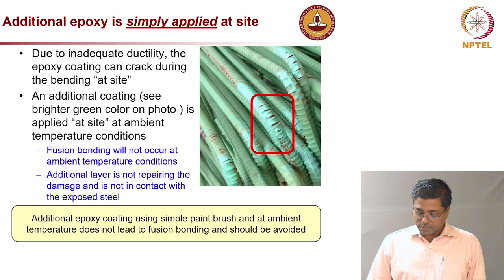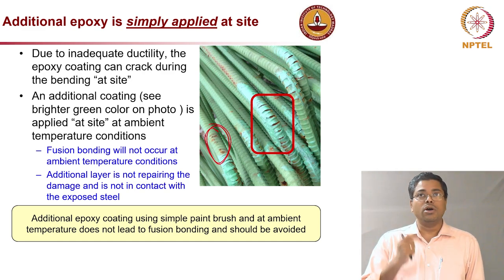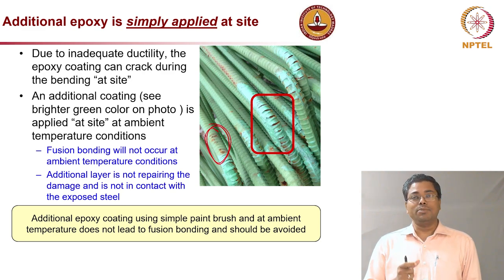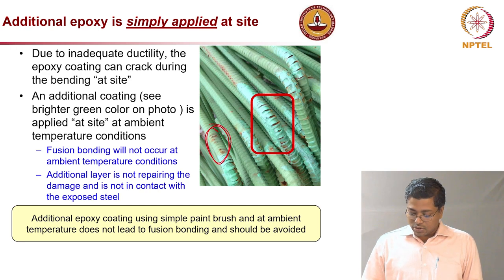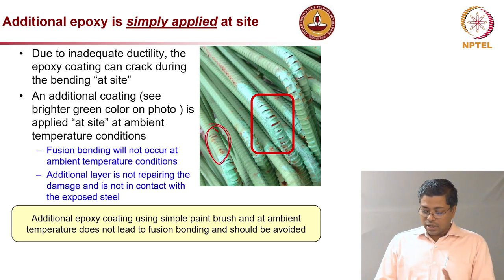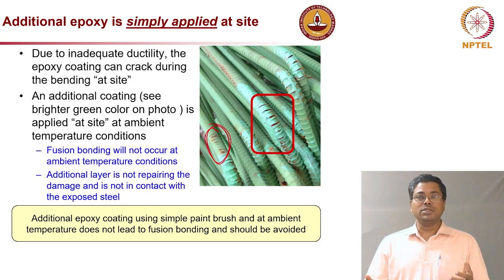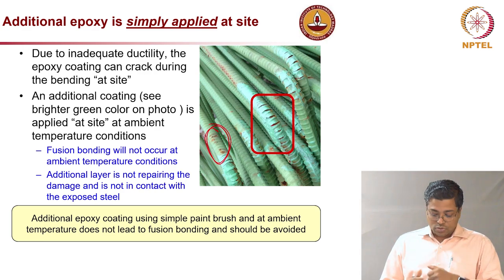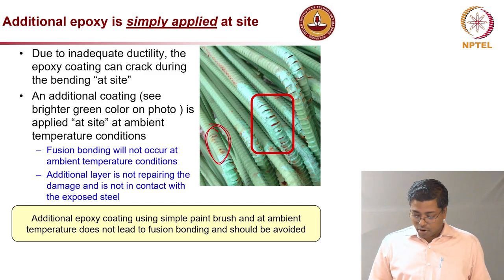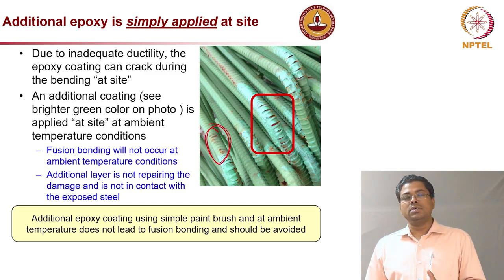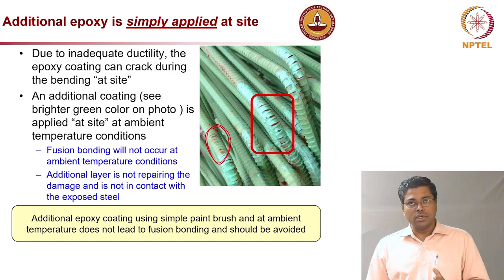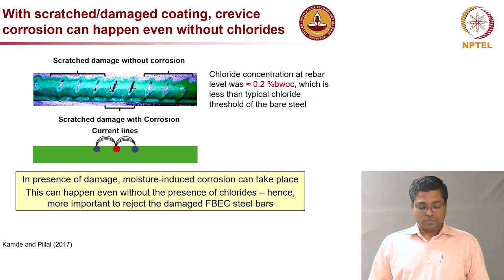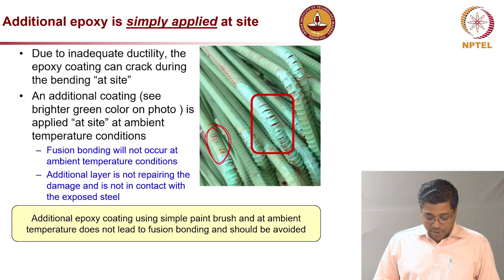The damages caused by pinching of the lever arm, and if the epoxy doesn't have good elastic properties at the time of bending, will lead to cracks at the bend region. These are bars with just 90-degree bends — imagine stirrups for earthquake-resistant designs bent to 135 degrees. The best practice is to bend before epoxy coating, not after.